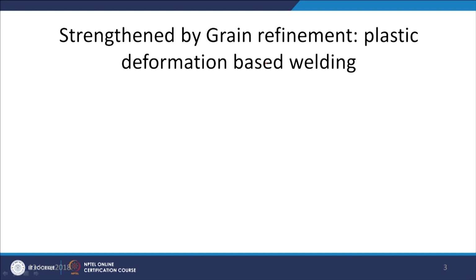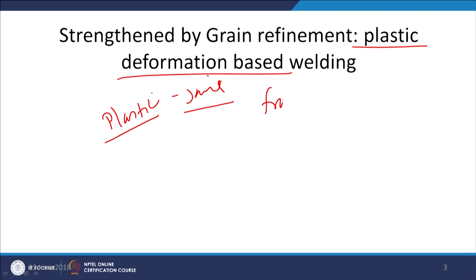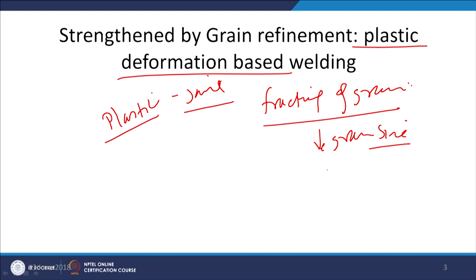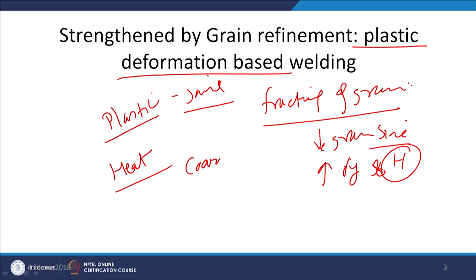Now, we will see when the metal system strengthened by grain refinement is subjected to welding through the plastic deformation approach. Whenever material is subjected to severe plastic deformation for development of the joint, a lot of fracturing of the grains is involved, which in turn lowers the grain size, and a reduction in grain size increases the yield strength, and also it increases the hardness of the metal. So, if heat is generated during the plastic deformation, then certainly it will cause the coarsening of the grains in the heat affected zone.